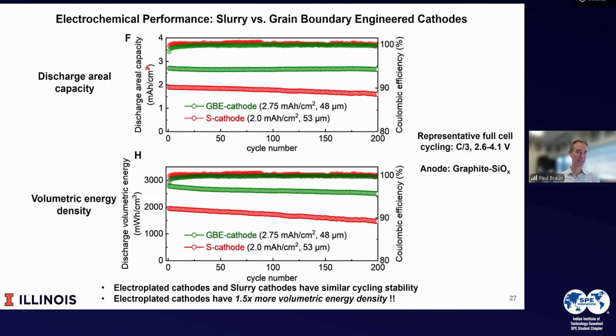And because of that, it cycles quite well. If we look at the grain boundary engineered cathode, it has a higher areal capacity because it doesn't have dead material. And so both from an areal and volumetric, it's substantially better. And these are cycled at C/3 from 2.6 to 4.1 volts. So the slurries, which are highly engineered as commercial material, our simple electrodeposited materials, which do not have any of that surface treatment, has similar cycling stability and 1.5 times the energy.